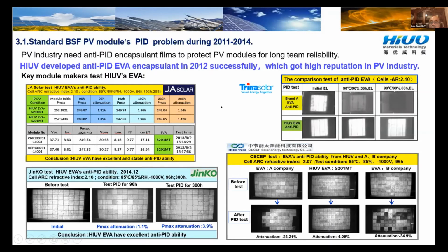Okay. For Trina, they tested our EVA against brand A. They did a one-cell level test, covered with copper foil to accelerate the PID. We are performing much better than the other ones. So this is Jinko. They also tested about 300 hours. They got a Pmax attenuation of only 3.9.